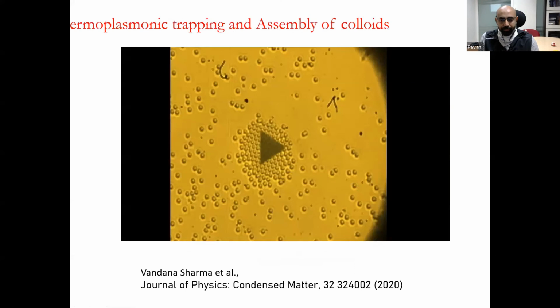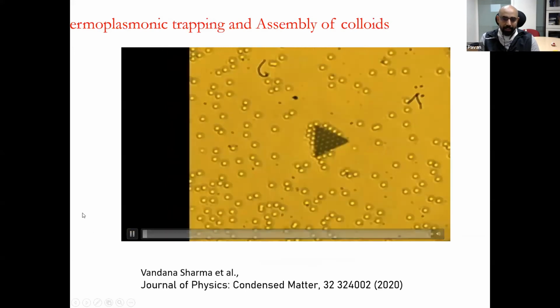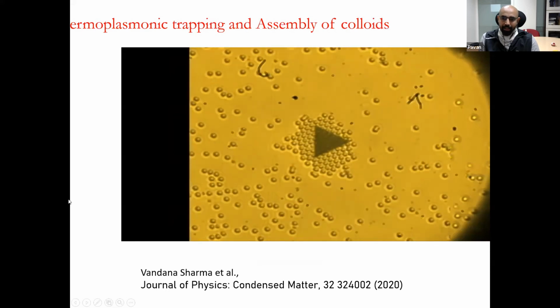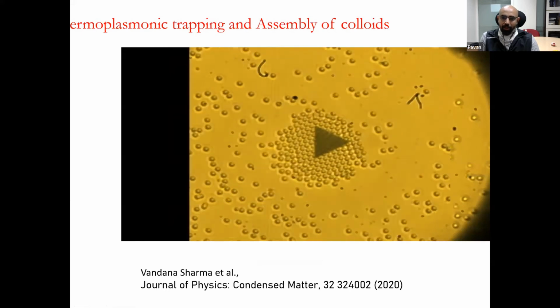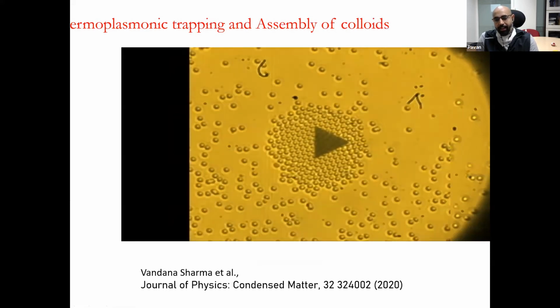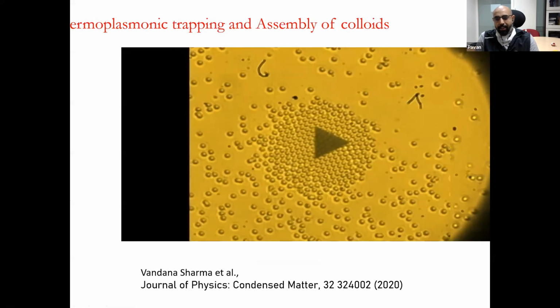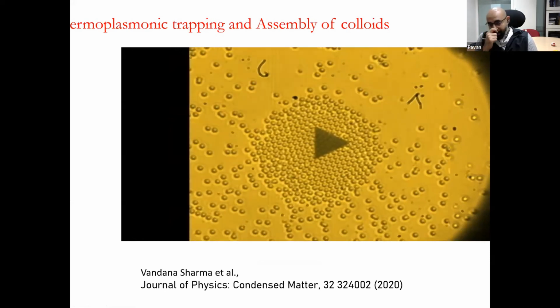Now we also are trying to do this in such a way that we can perform something called thermoplasmonic trapping and assembly of colloids. This is a technique which we have developed on a single crystalline gold triangle, where you excite this single crystalline gold triangle and you start seeing assembly of colloids around the triangle. And this is all happening on a colloidal substrate.